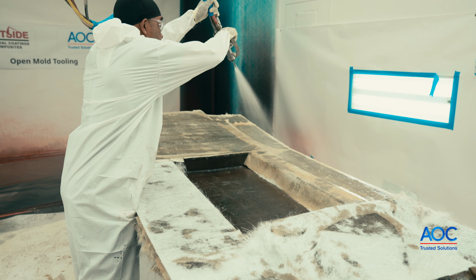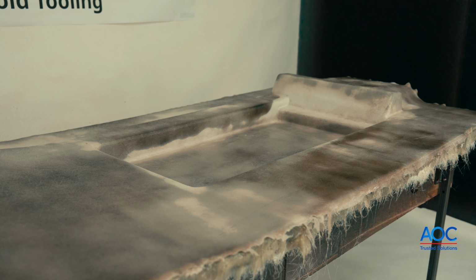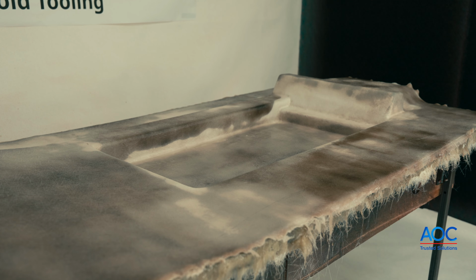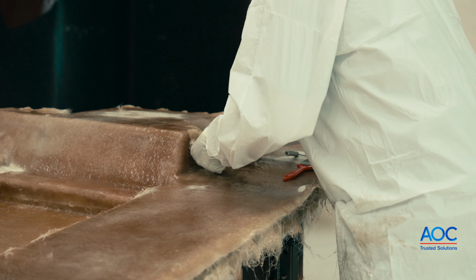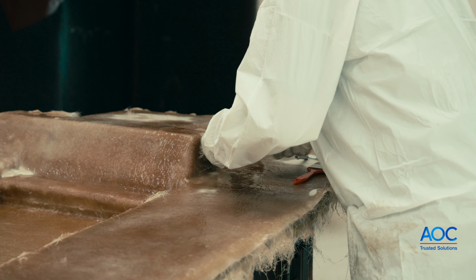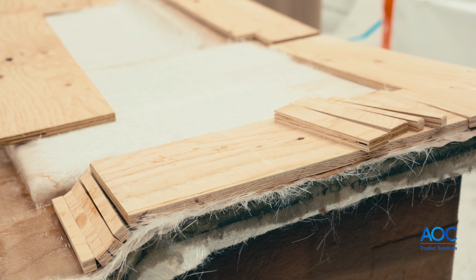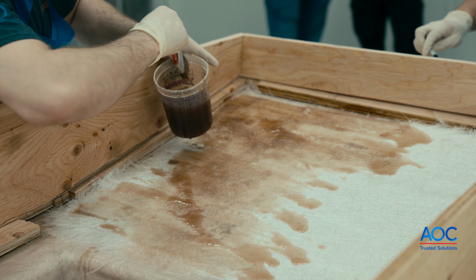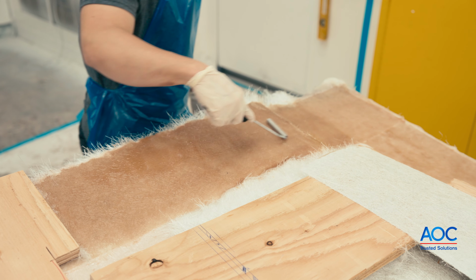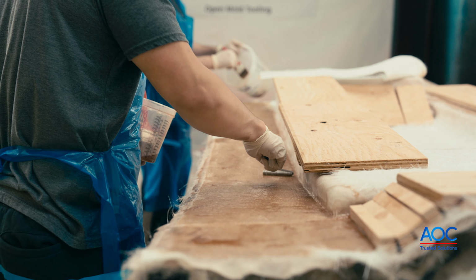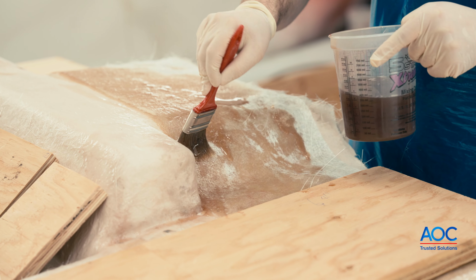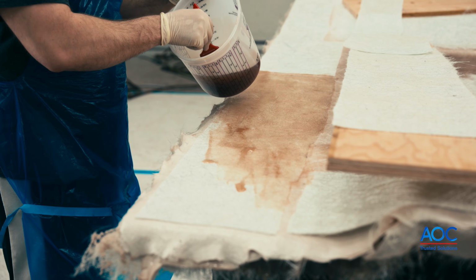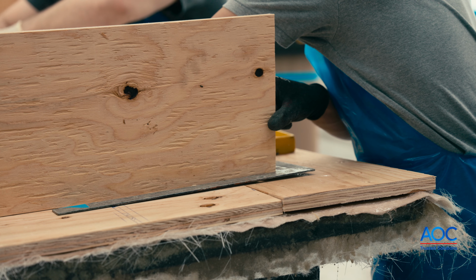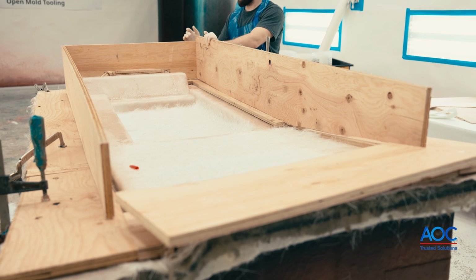The resin will heat up as it cures, so it's important to wait for each layer to cool before applying the next layer of 3 to 5 ply. Continue layering until the maximum thickness is reached. Over time, the tool should turn completely white, indicating the process was successful. Depending on conditions and gel times, the lapse time between layering is approximately 1.5 to 3 hours. After the third layer, an optional balsa wood or foam core can be applied for additional stability.